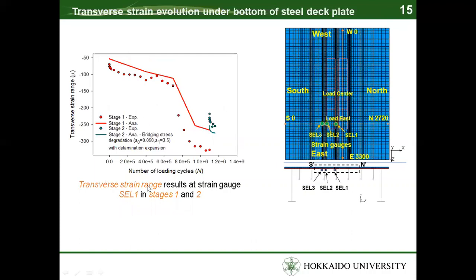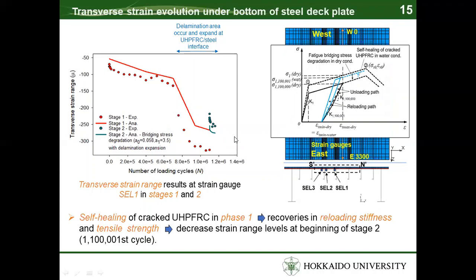This figure shows the transverse strain range result at the strain gauge SEL1 in the steel deck plate. In stage 1, due to the occurrence and expansion of the delamination area at the UHPFRC steel interface, a significant increase in transverse strain range can be observed, as in this figure. And after that, in stage 2, under surface water conditions, due to the recovery in reloading stiffness and tensile strength caused by the self-healing of UHPFRC, a decrease in strain range level is obtained at the beginning of stage 2.